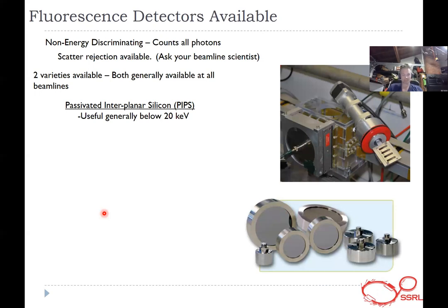We have a PIPS detector, which is personally my favorite. PIPS stands for passivated implanted planar silicon. Since it's silicon, its efficiency drops off with energy because it doesn't have the stopping power. It's not high enough Z to stop high energy photons, although that is changing as they're making them thicker and thicker. We'll probably move away from Lytle with time, which is what we'll talk about next. The thickness of silicon increases the probability that a photon interaction with the silicon will occur, creating signal. It's a simple explanation. The more photons you can stop, the better signal you get. With thin silicon, that's not always the case.